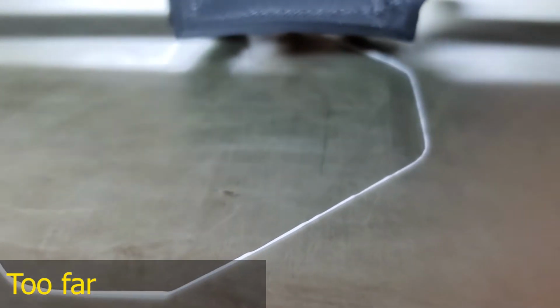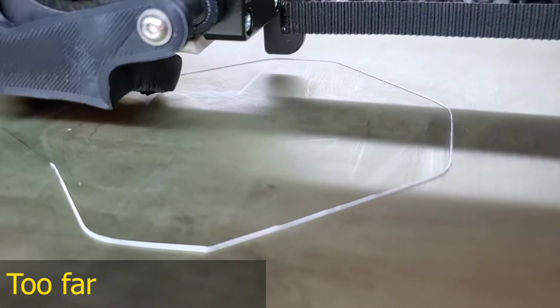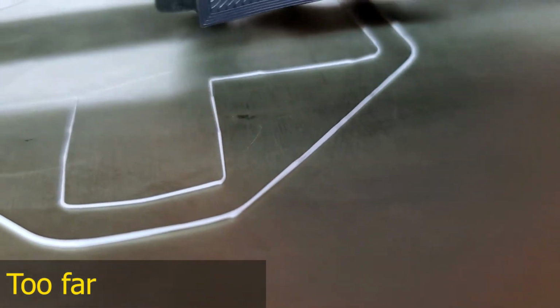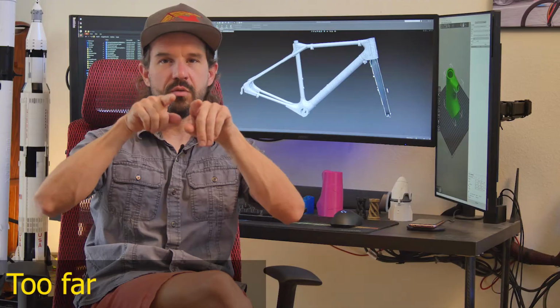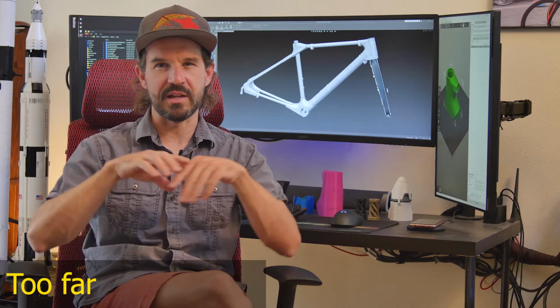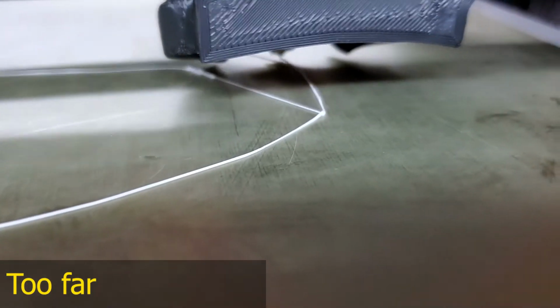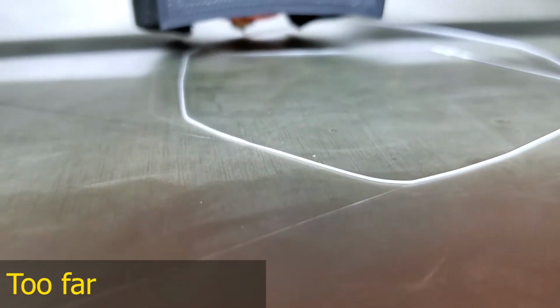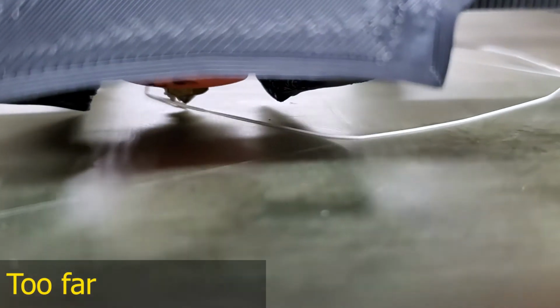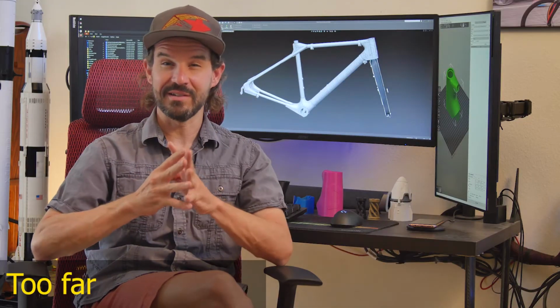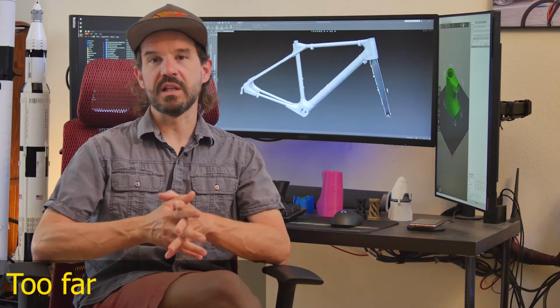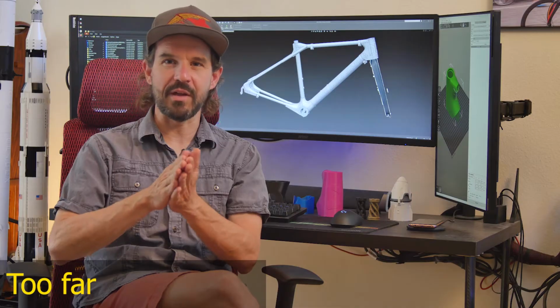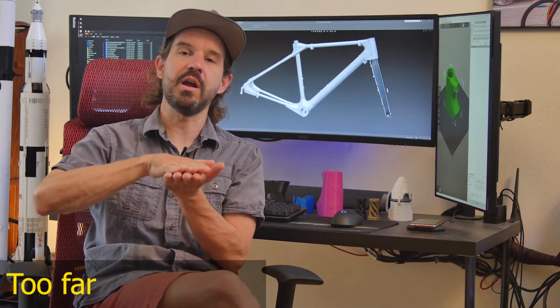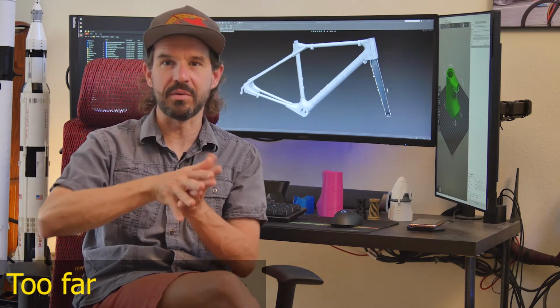Now we've got the Z offset too high. The cross-sectional shape of the extruded filament will be just about circular, and you will not notice squish down at the sides. The material might not stick in the corners, and arc moves, curved shapes, will likely end up as straight lines. Individual perimeters or the brim will not be touching. Again, you might be able to get away with printing like this, but you're much more likely to have a print failure due to the part coming off the bed because it's not properly stuck down.